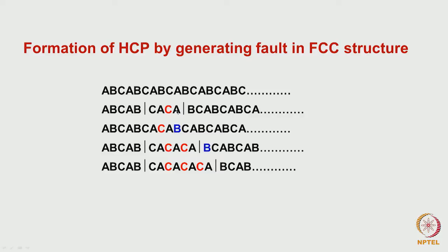this is a layer, this is the next layer, this is being moved to another layer, okay. That is not this layer, I said alternate one. Alternate one means that you leave this and come to the next one. So this B layer is again shifted, then it will go to a C position. This is how the stacking sequence is. Then the next alternate one, if I move it, then this B layer will come to a C layer. Now if you look at the stacking sequence, this is ABC. Now we are able to form CA. That means an AB type of stacking sequence.